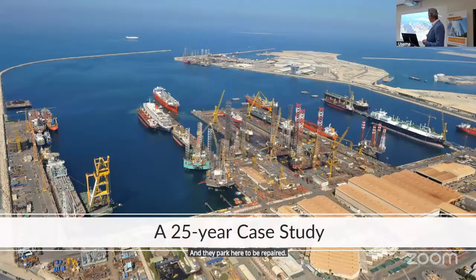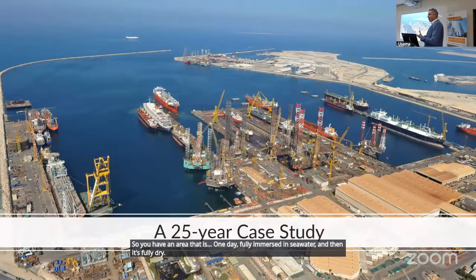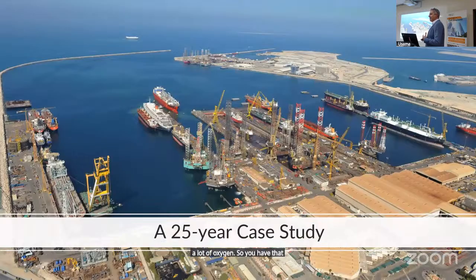A gate closes. If you see the dock next to it, this is dry because the gate closes and they drain the water out. So you have an area that is one day fully immersed in seawater and then it's fully dry, a lot of oxygen. So you have that cyclic, the most aggressive exposure, the cyclic exposure to salt water.